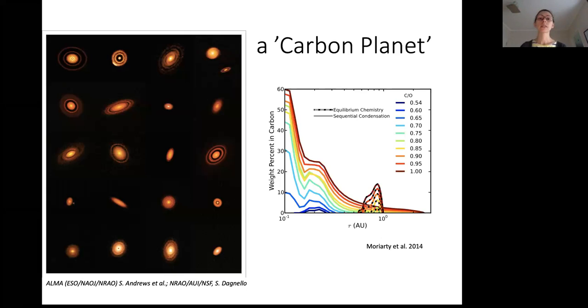And it was proposed that some stars that were very carbon rich would then give rise to carbon rich planets orbiting them. And so this figure I have here on the right, these are model results looking at how the carbon to oxygen ratio, which is varied in these rainbow colored lines, with blue being a low ratio and red being a high ratio, affects things. If you look at the distance from your star, which is the x-axis here, and the weight percent of carbon that is precipitating out to form your planets in your disk, at high carbon to oxygen ratios you have quite a high amount of carbon-rich material available to make your planets. So in a system like this, you would be forming your planets out of carbides like silicon carbide or iron carbide, rather than out of the materials that an Earth-like planet is made of, like silicates.